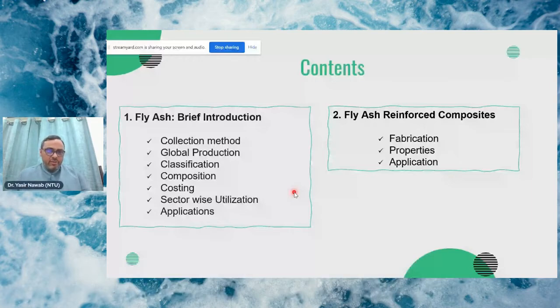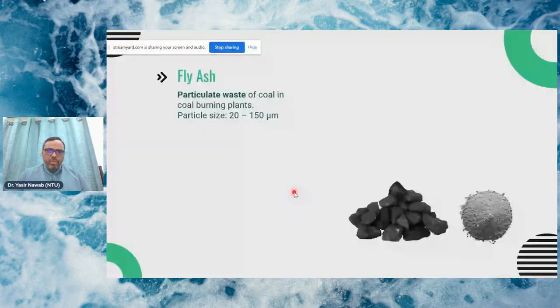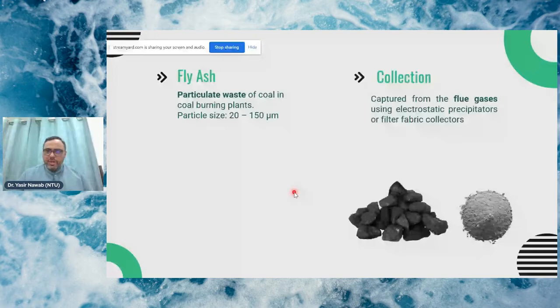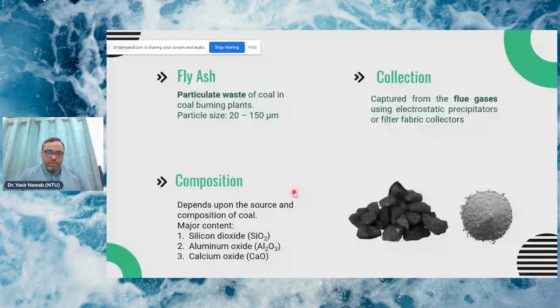So fly ash, in fact, is a particulate waste of coal in coal burning plants. The particle size in the fly ash is about 20 to 150 micrometer. So generally, we capture the fly ash from the flue gases using electrostatic precipitators or filter fabric collectors. The composition, in fact, depends upon the source and composition of coal. The major contents include silicon dioxide, aluminum oxide, calcium oxide, etc.